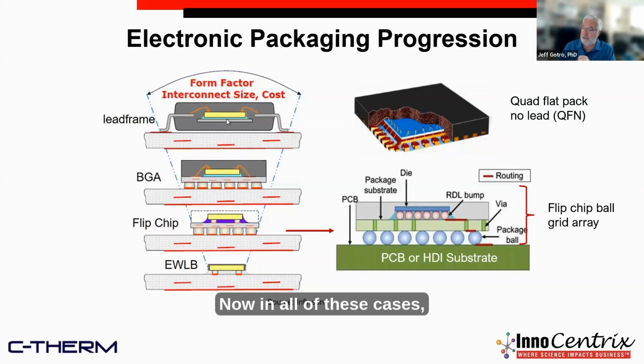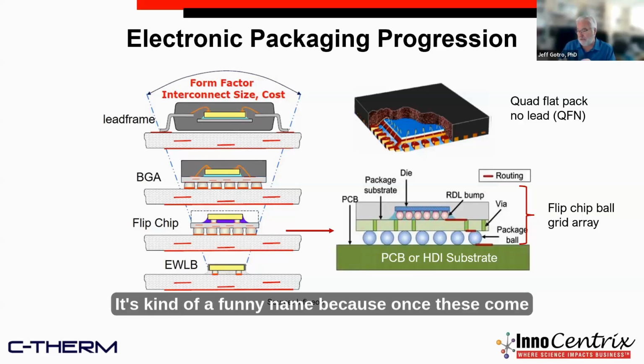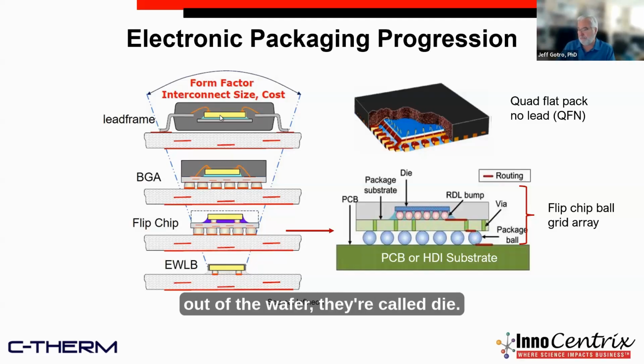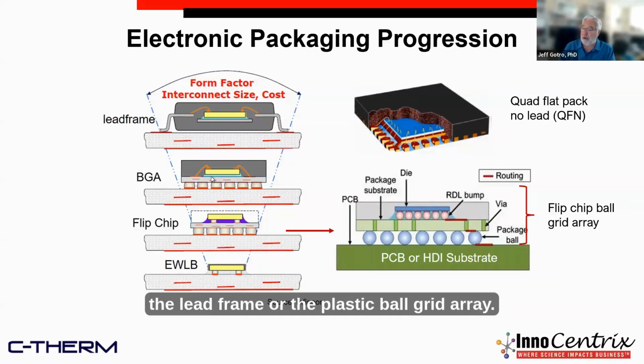Now, in all of these cases, you can see this teal right here is the die attach adhesive. It's kind of a funny name because once these come out of the wafer, they're called die. And then this teal is a die attach adhesive. So it's a highly engineered adhesive, thermally conductive, electrically conductive, that adheres the semiconductor chip down to this, in this case, the lead frame or the plastic ball grid array.